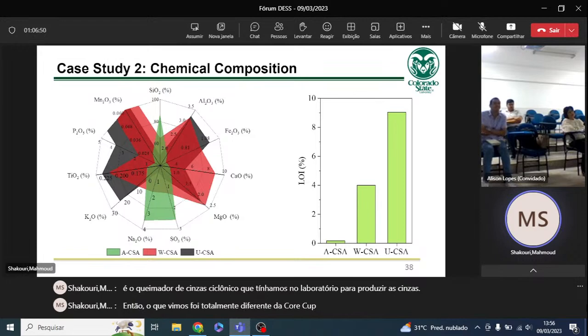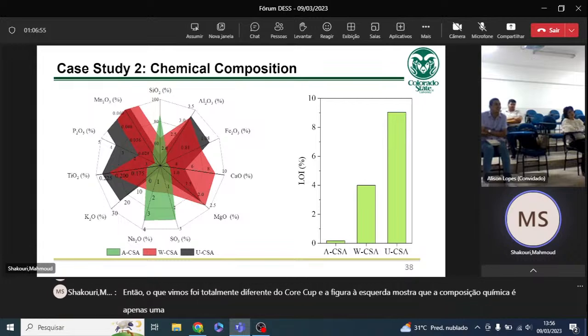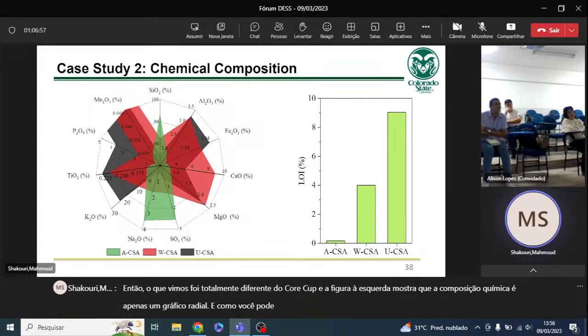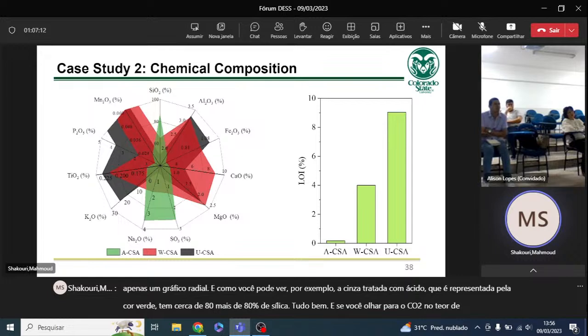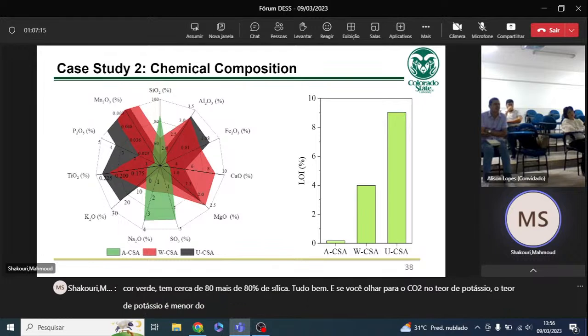So what we saw was totally different from the corn cob. The figure on the left shows the chemical composition. It's just a radial plot. And as you can see, for example, the acid-treated ash, which is represented by the green color, has more than 80% silica, all right? And if you look at the K2O, the potassium content is less than 5%. So from 30% in corn cob, we went down all the way lower than 5%, which was a huge improvement.